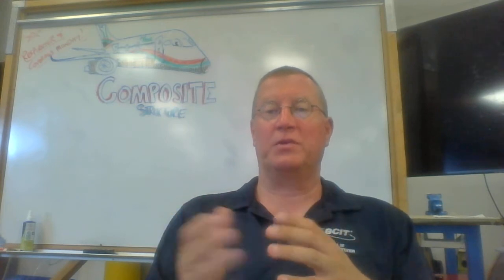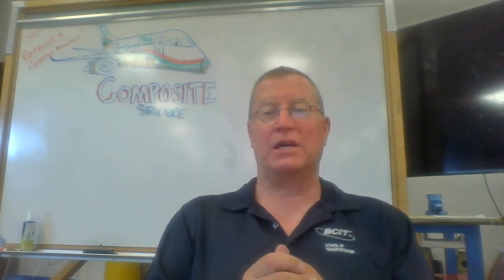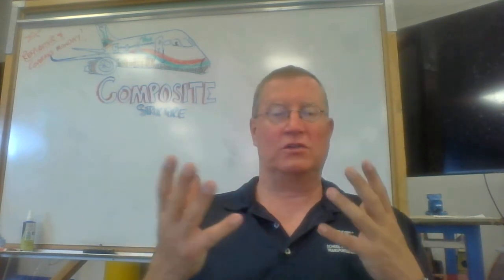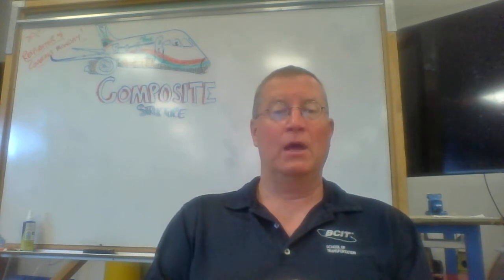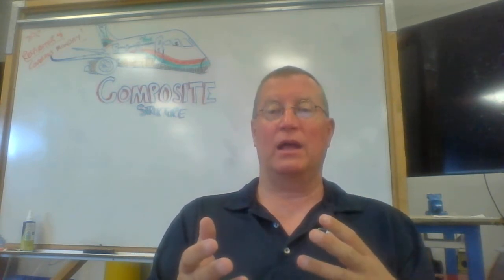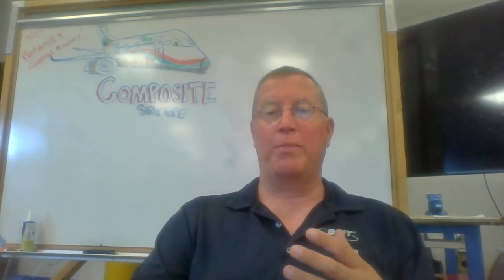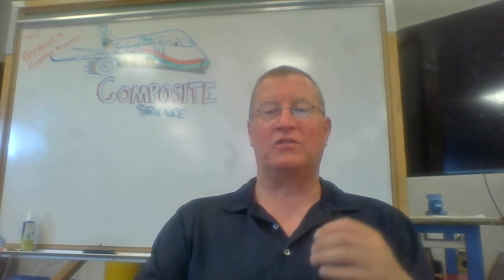If we think there's the potential that there may be delamination via doing some sort of a tap test, then we're going to get NDT involved to verify, unless the damage is subvisual, and then we're going to have to carry out some sort of repair. If it's a strong load-bearing type component, then we're going to be looking for something like a step repair.